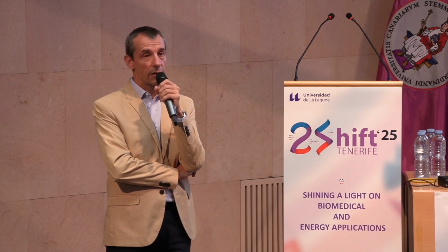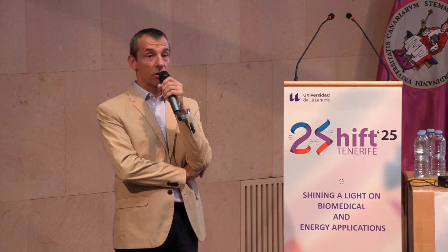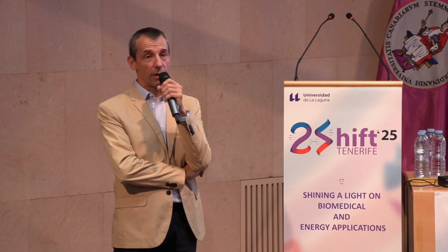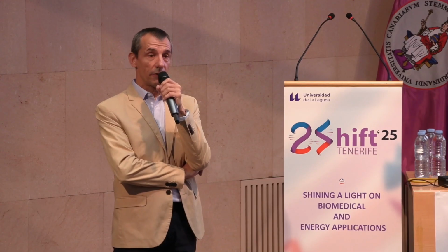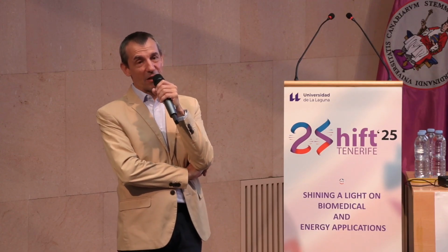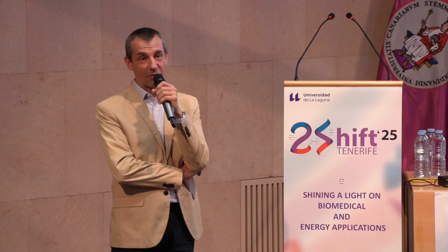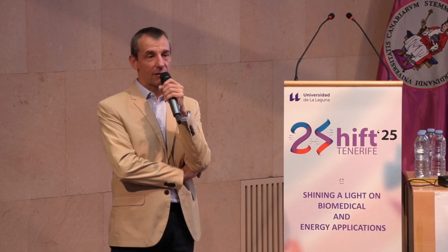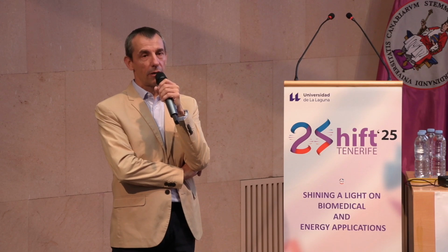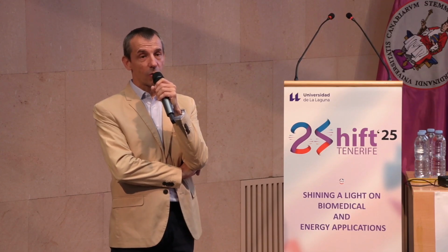Yeah, I think lithium niobate is actually extremely interesting. A lot of work is going on, and it's related to integrated photonics, in my view, because in lithium niobate you can get these nice structures with very low losses. You can make resonators and waveguides with very high performance, and it's an electro-optic material, so you can also tune the properties by electric field, which is not the case with silicon, for example. And for rare earth ions, it's even more potentially interesting because you can readily dope lithium niobate with rare earth ions. The only problem is that lithium niobate is a host with a high nuclear moment density. So you have the spins of lithium and niobium, and this is causing a lot of magnetic noise.